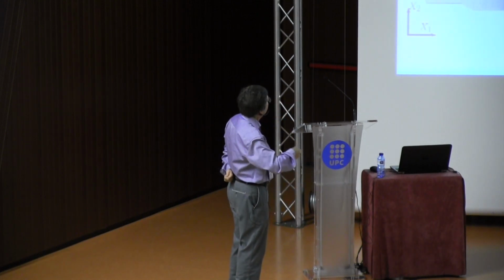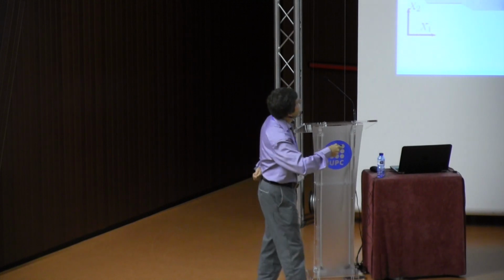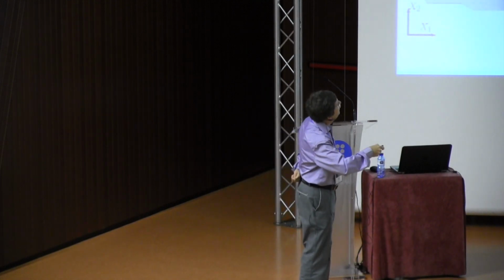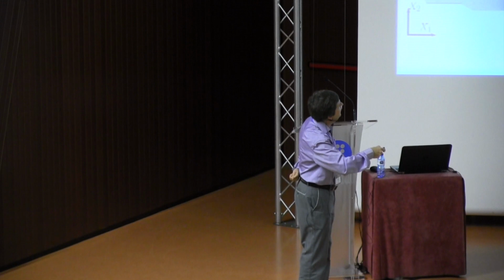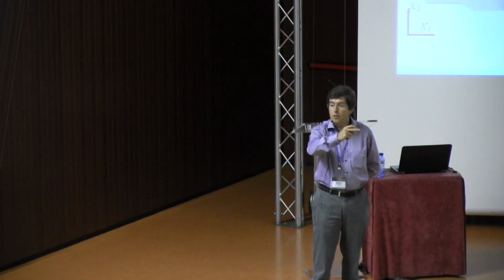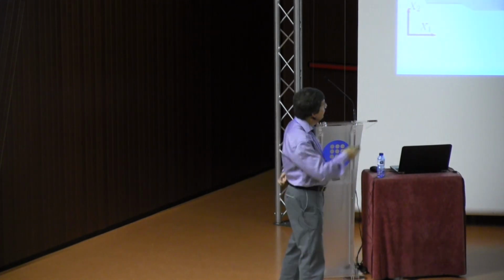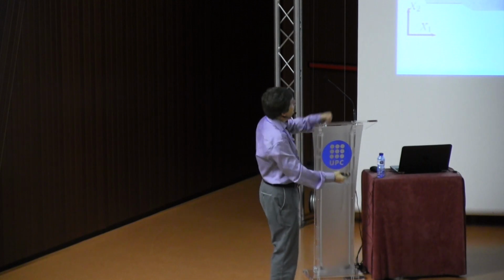Here you have a crack in a CT specimen of single crystal, and this is the experiment here, and you see that there are slip lines, so we can really use crystal plasticity to predict the plasticity in front at the crack tip, in fact.